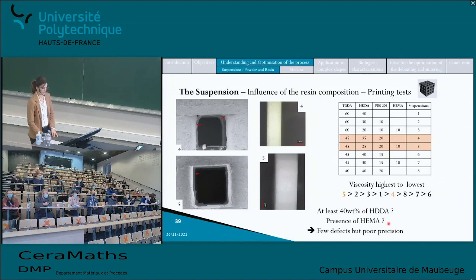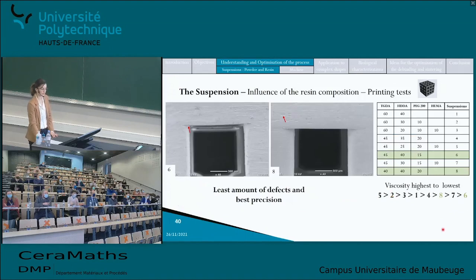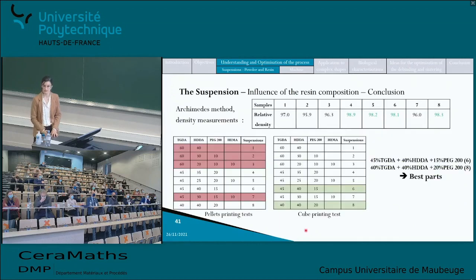So finally, suspensions 6 and 8 were the ones providing the best samples in all of the experiments. Here there is better precision compared to the other samples, and there are only a few defects on their surface with very small delaminations. So I added to that some density measurements done by the Archimedes method. And here suspension compositions 4, 5, 6, and 8 were the ones providing the samples with the highest densities, with a relative density above 98%.